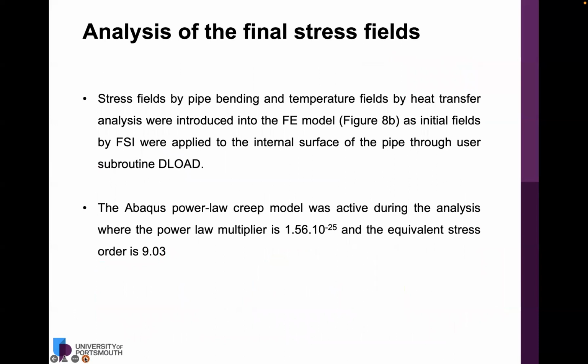So using the stress fields and the temperature fields for our initial conditions in the thermomechanical finite element models, which can be applied through user subroutine. And also we activated the Abaqus power law creep model during the analysis using these parameters, again, to allow us comparing like with like. So these are the parameters for the materials and the conditions that we are simulating. And all these are used in the final simulations using the combined residual stress and FSI model.